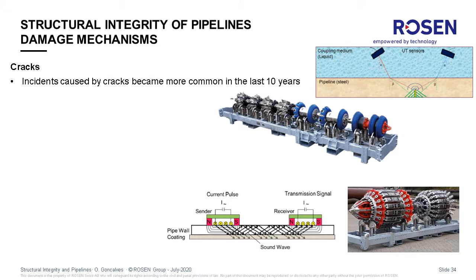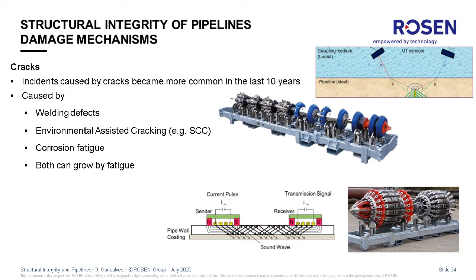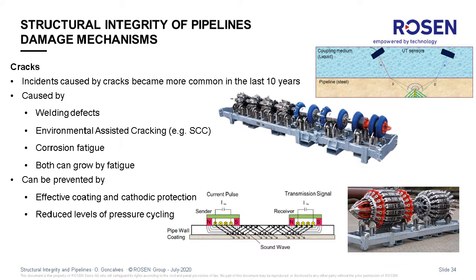Now, regarding cracks, cracking issues started to become more common in the last 10 years. There are different types of cracks that can be present in the pipeline. Most of them are caused by welding defects, also by environmentally assisted cracking like SCC, stress corrosion cracking, corrosion fatigue, and any crack can potentially grow by fatigue due to pressure fluctuations and pressure cycling in the pipeline operation.